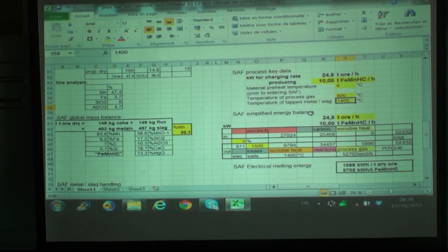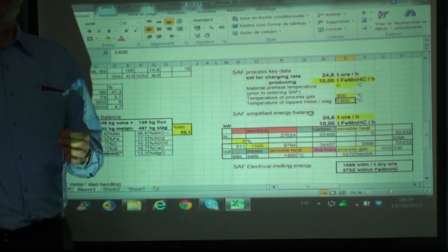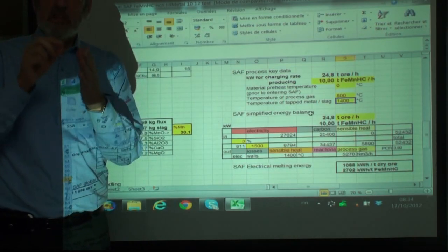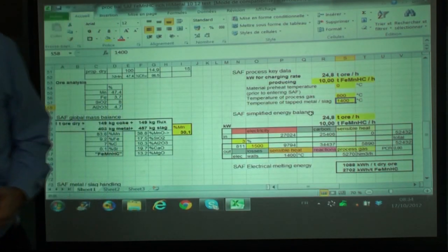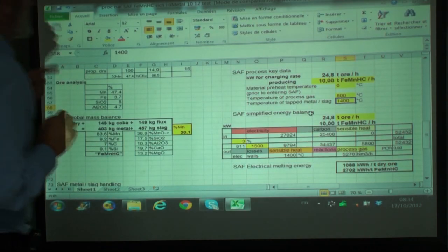For the gases, the data are well known. You can use a table giving you the enthalpy at 0, at 100, at 200, etc. But if you want to do this, you can do it. It's possible. But I simplify it because I just assume that it is linear. In reality, it's not completely linear. But the biggest uncertainty is the choice of this temperature. Is it 700 or 800 or 600?